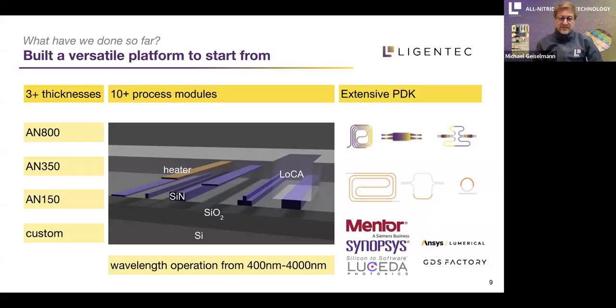And why do we have different thicknesses? This is mainly to cover wavelength operation from 400 nanometer to 4 micron. So silicon nitride has the advantage that you have a very broad transmission spectrum, but the waveguide needs to be adapted if you have a very short or very long wavelength region. And one of our core competences is to have a very confined mode in the waveguide, so we can combine very low losses with a very good confinement. And that platform goes with an extensive PDK.